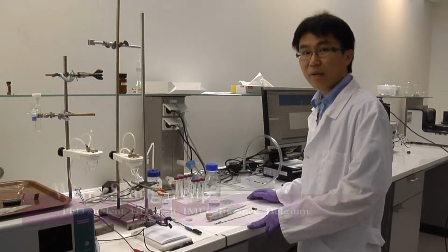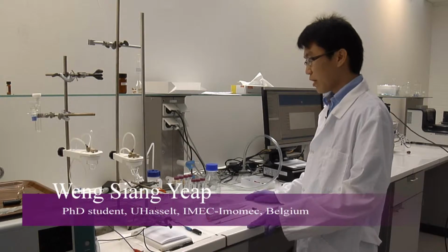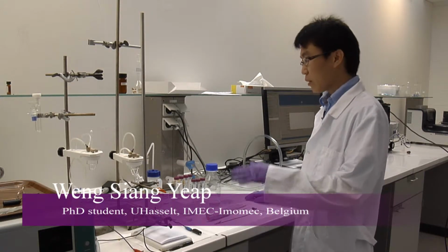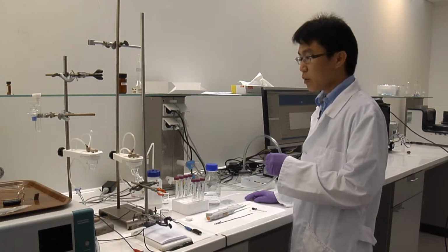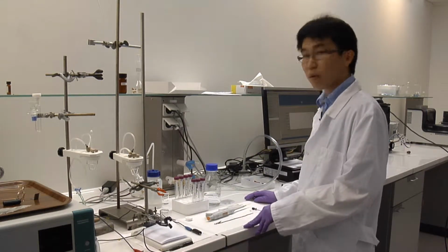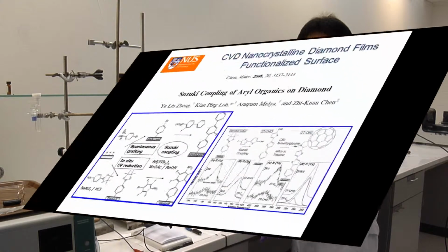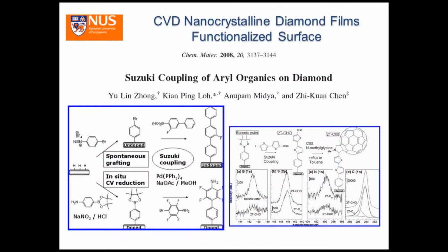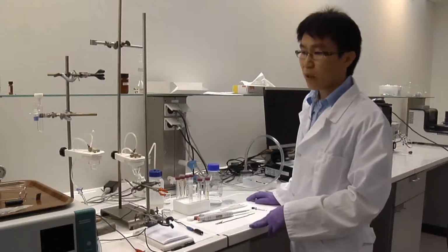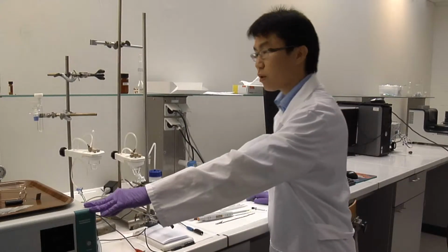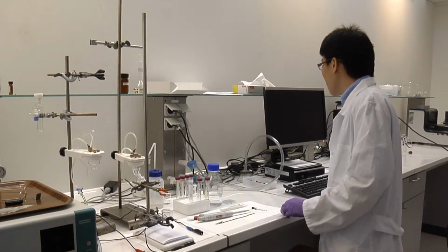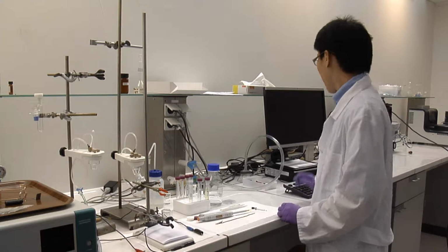We will use cyclic voltammetry scan techniques to functionalize the diamond surface with aryl boronic esters, so that the functionalized layer can then be used as a platform for subsequent Suzuki cross-coupling reaction with the molecular dyes. The cyclic voltammetry functionalization will be performed using a potentiostat controlled by a GPES software.